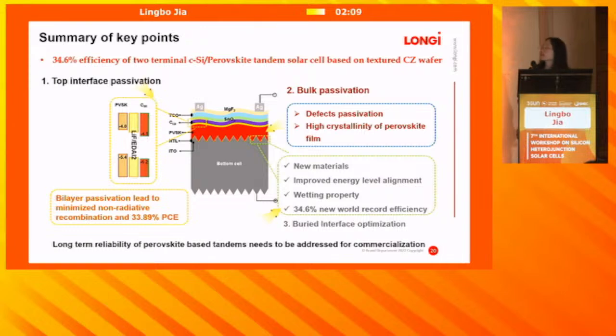We focused on the interface passivation and also the bulk passivation. Here, first we introduced a bifunctional layer between carbon-60 and perovskite to passivate the defects at this interface and minimize non-radiative recombination, finally leading to 33.9% performance. And then we have also focused on the bulk passivation. We use a bifunctional material additive to passivate the defects at the grain boundaries and fill the halide vacancies simultaneously. And finally, the higher crystallinity of perovskite films and a long charge carrier lifetime lead to the reduced VOC loss.